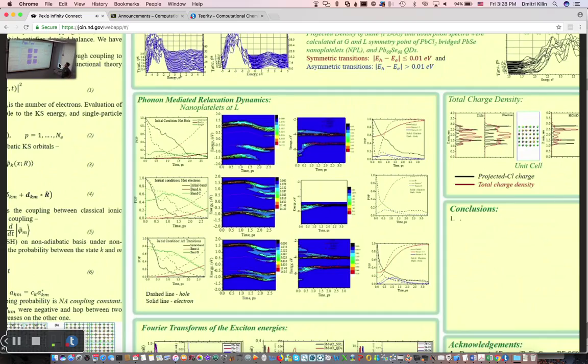If you look at similar conditions with the quantum dot system, first of all, something very significant is observable. It is relaxing to the frontier orbital very quickly compared to the 2D nanoplates. If you look at the population, the red line is the population of frontier orbitals, the HOMO and HOMO-1 to HOMO-4.